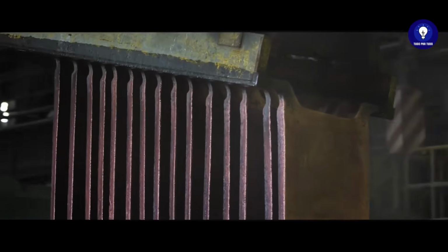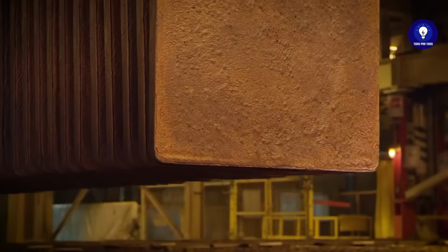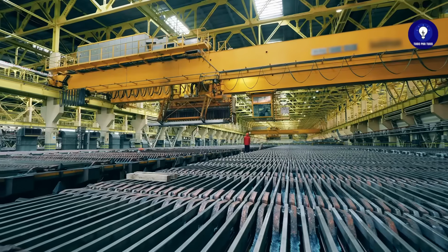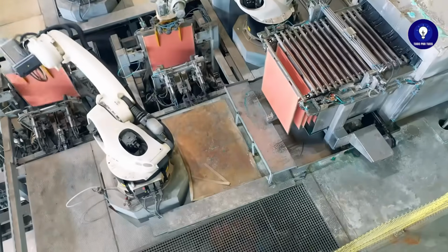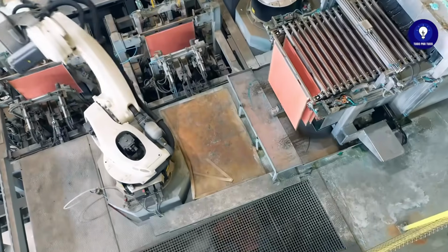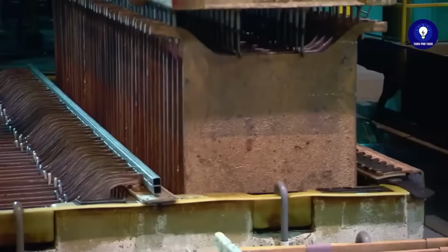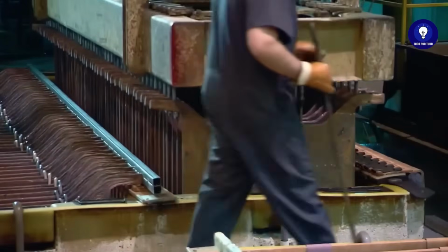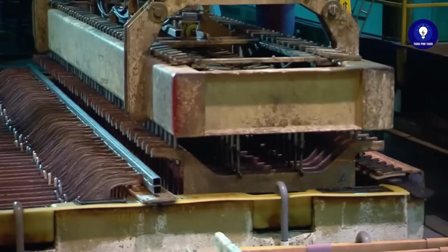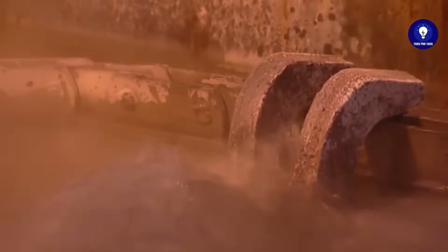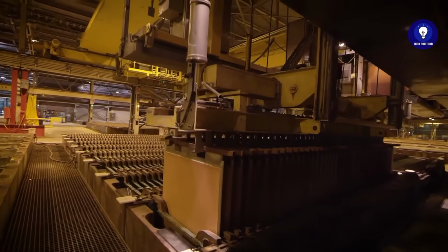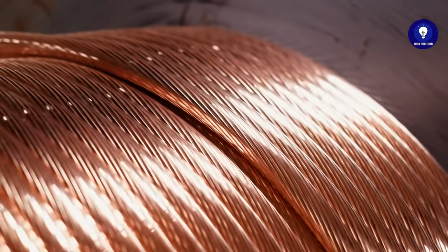At the refinery, maximum purity is achieved. The anodes are immersed in tanks with electrolyte and placed in front of thin metal sheets called cathodes. When an electric current is applied, the pure copper transfers from the anodes to the cathodes. The impurities fall to the bottom of the tank. The result is copper with almost 100% purity, suitable for manufacturing high-performance cables.